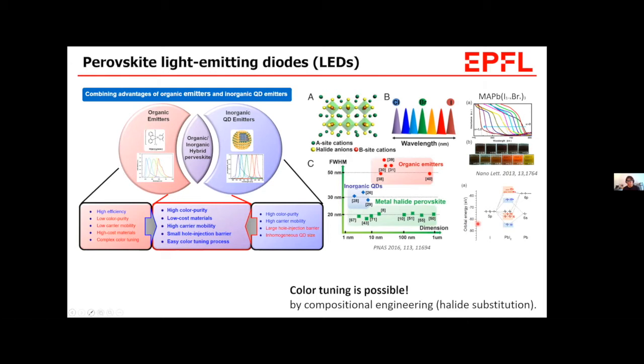From iodide to chloride, the band gap widens, so we see this blue shift. The band gap narrowing or widening is associated with the electronic structure, again, of lead halide, as we discussed before. So the use of bromide or chloride will drag down this orbital compared to when we used iodide. So we have a wider band gap and a blue shift. So the use of perovskite emitters can realize various color emission as you wish, and this can ultimately achieve white perovskite LEDs, either based on an RGB system or a tandem structure.